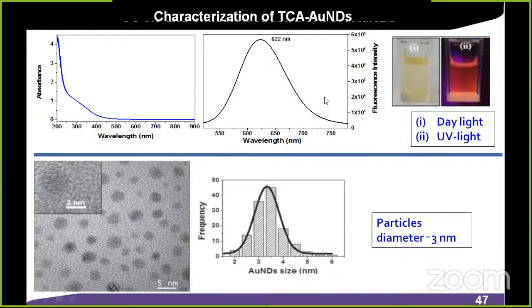So they have to wait for 12 hours, 24 hours, in dark room conditions with very expensive chemicals. But with small molecules at room temperature, we have prepared these nanodots. And also, fortunately, it shows red emission. See here, 622. This is the particle size. Particle size has been calculated to be 3 nanometers.